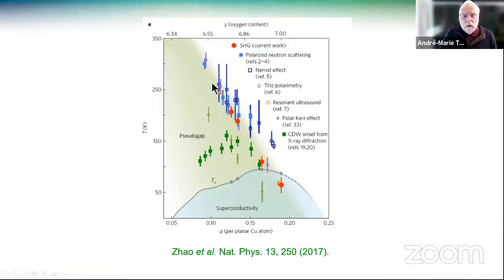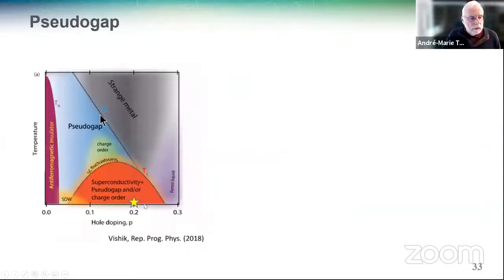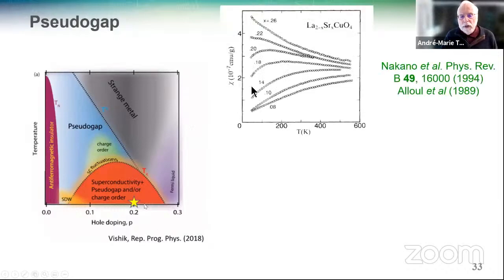So, pseudogap. We had a talk by David Sénéchal that discussed many phase transitions here, and that's usually what is meant by T-star. But in reality, if we look at the early experiments, for example by Alloul and Nakano, if you look at the spin susceptibility as a function of temperature, you see that it's not an ordinary metal. A metal would have Pauli susceptibility, which is independent of temperature. Instead, you get this loss of spectral weight at the Fermi level that leads to this downfall of the spin susceptibility.